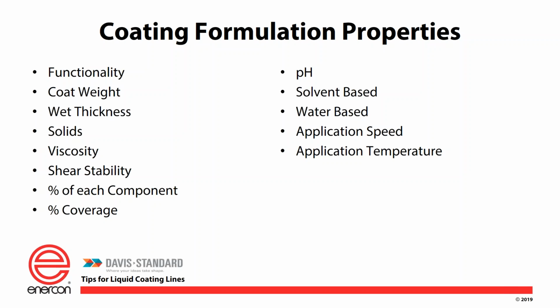And then percent coverage. In most cases, you're going to coat the entire web, right? And typically we leave a dry edge, especially with an adhesive coater. So a silicone will coat all the way to the end, whereas the adhesive will leave a little edge on the end that's uncoated, maybe 1/8 to 1/4 inch. This is so that the adhesive doesn't bleed out when you're winding it.